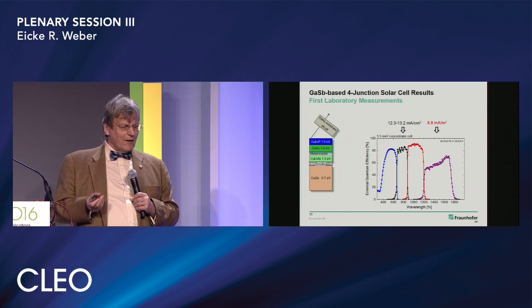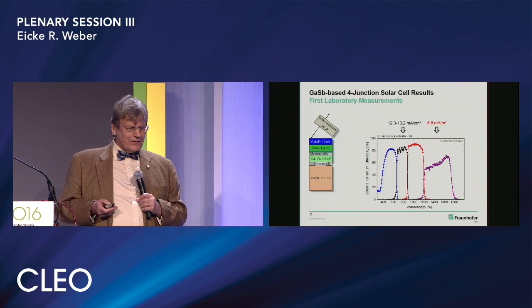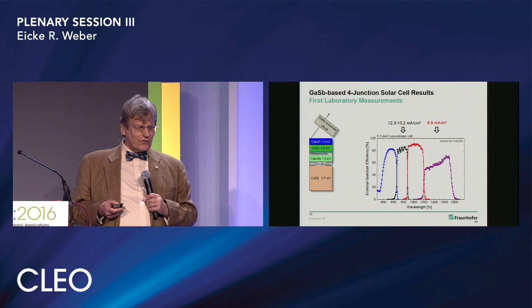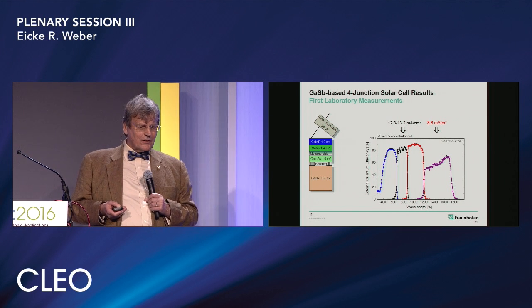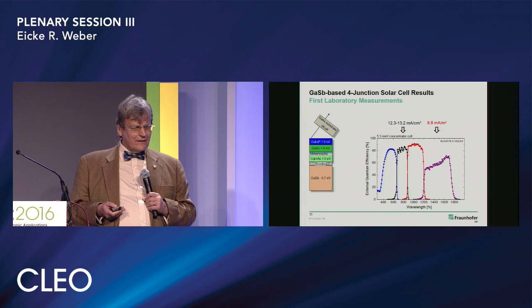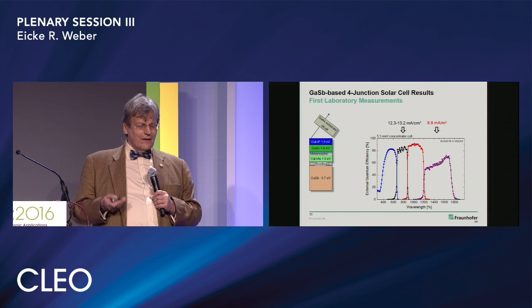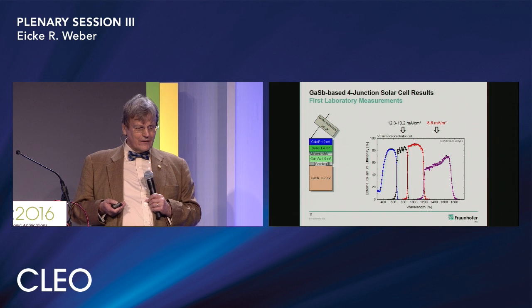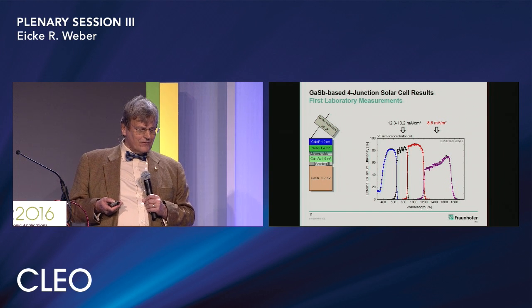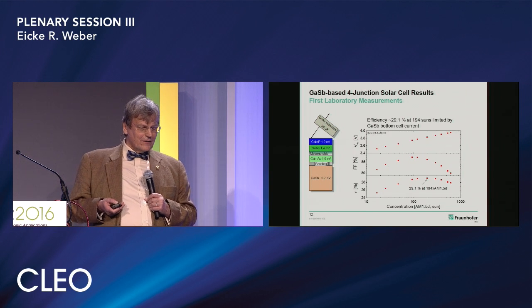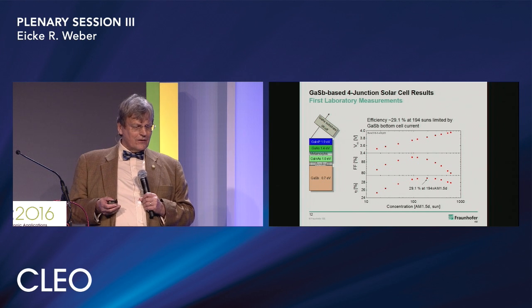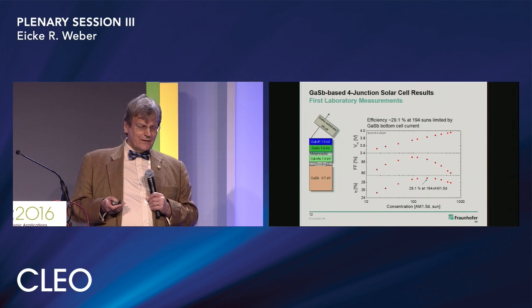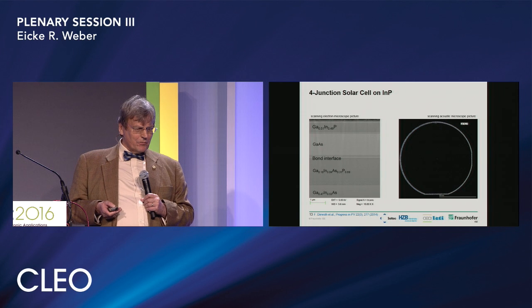Now we come to a gallium antimonide based 4-junction solar cell. You see the gallium antimonide layer is the weak link. Here we have a very poor current matching because we don't get the same amount of current, but you see we can harvest solar energy far out into the infrared till about 1,800 nanometers. And with such a structure, 29% was the highest efficiency possible.